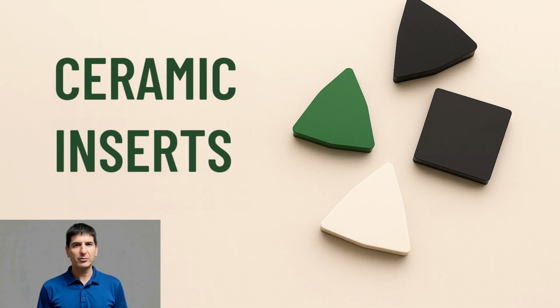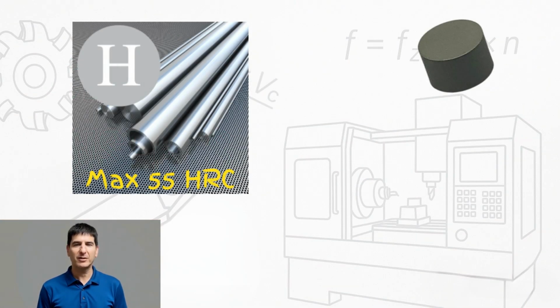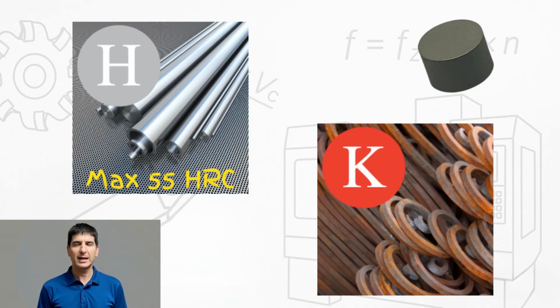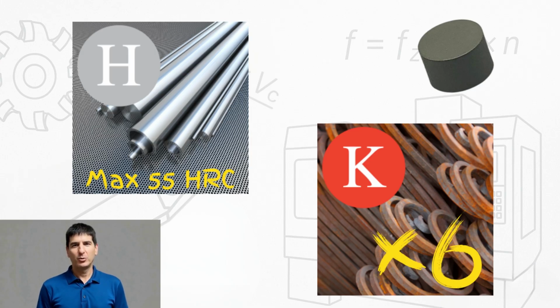Ceramic inserts are made from aluminum oxide or silicon nitride. At 2100 to 2500 HV, they sit between carbide and CBN, but at a much more affordable price point. For hardened steel up to 55 HRC, ceramics provide an economical middle ground between carbide and CBN. In cast iron, they can run 6 times faster than coated carbide, making them a popular solution in many production lines where high productivity is a priority.